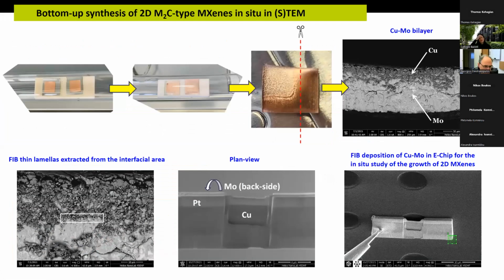So what we did step by step to achieve in situ growth in TEM: the sample preparation was a tricky part. You can see here that we had these two metallic foils, molybdenum and copper on top. We heat it up, so you can see here, or even better here, that the copper melted, covering the whole substrate. Here you can see a cross-sectional SEM image.